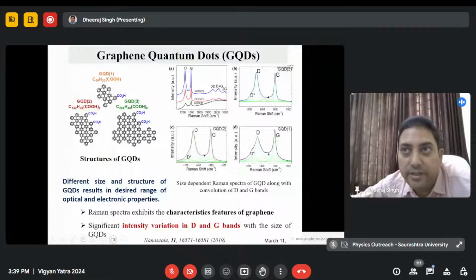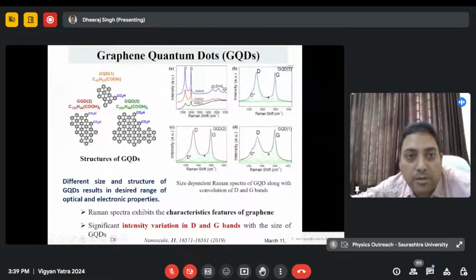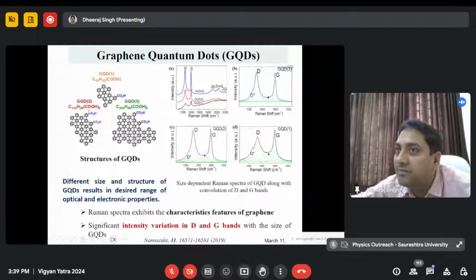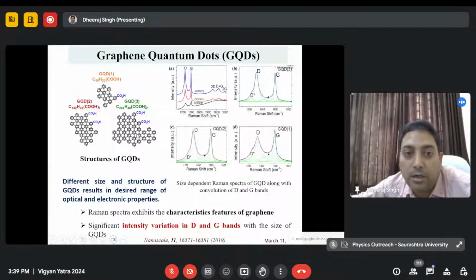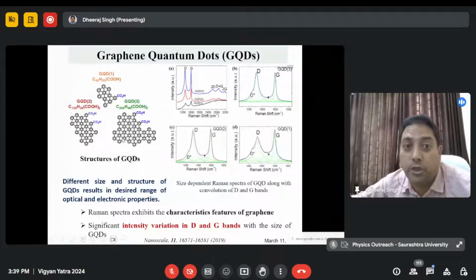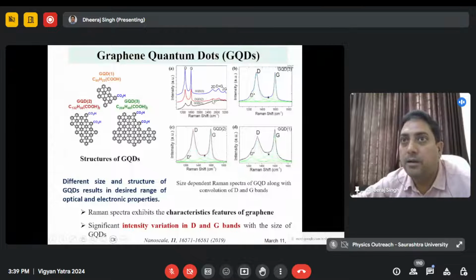A simple example is graphene quantum dots. In this Raman spectra, we can see that in the first molecule, graphene quantum dot 1, there is COOH functionalization. In the second spectrum, graphene quantum dot 2, we have functionalized with two carboxylate groups. In the third molecule system, we have increased the size of the quantum dot, and two carboxylate COO functionalizations are present. Now let us see the Raman spectra of the corresponding structures.